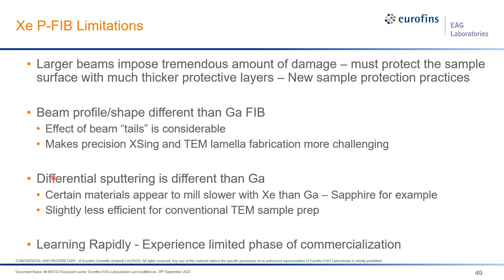It's also important to understand that the beam profile and shape of the PFIB ion beam is a bit different than gallium FIB. So there's quite an effect of the beam tails as well. It's quite considerable. So we have to change the way we fabricate precision cross sections and TEM lamella a little bit, and it can pose some more challenging aspects to that.